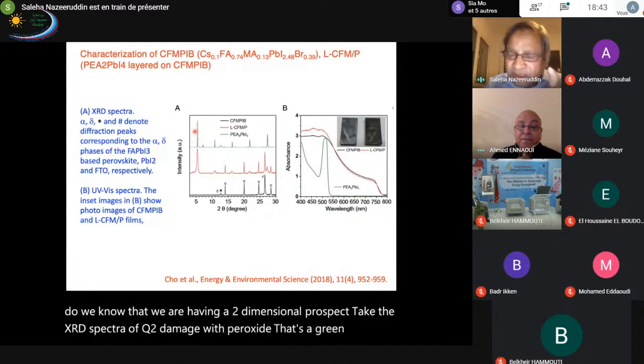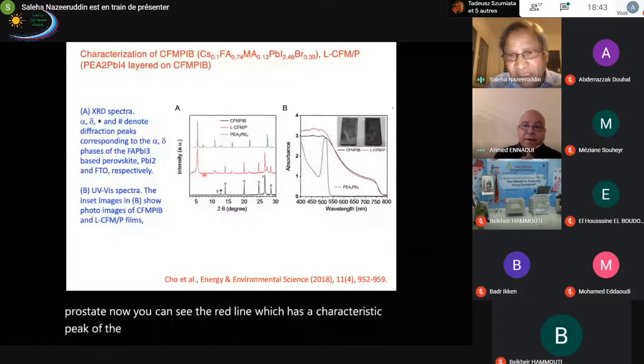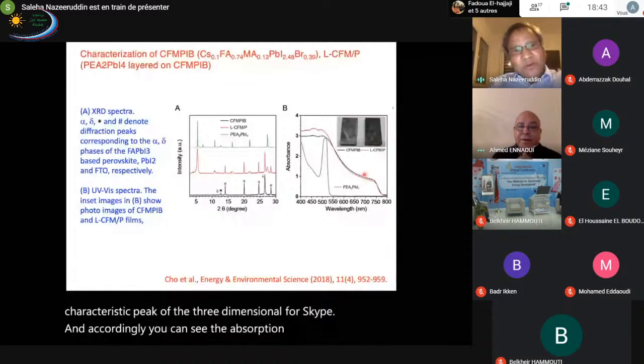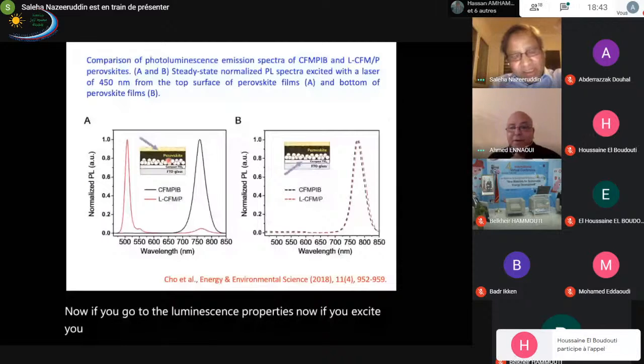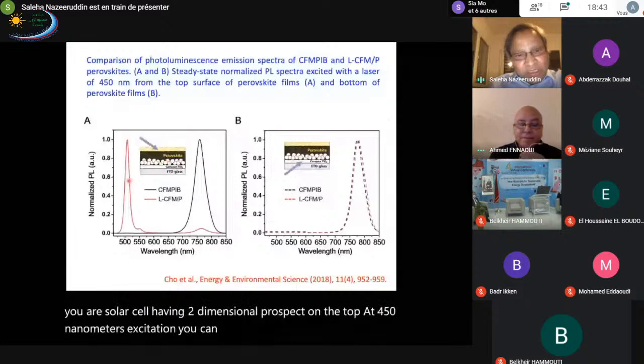Now, when we deposit the two-dimensional perovskite on top of the three-dimensional perovskite, you can see the red line, which has a characteristic peak of the two-dimensional perovskite, and at the same time a characteristic peak of the three-dimensional perovskite. Accordingly, you can see the absorption spectral properties reflect that. Now, if you go to the luminescence properties, if you excite your solar cell having two-dimensional perovskite on top at 450 nanometers excitation, you can see only the two-dimensional perovskite got excited and it's giving emission.